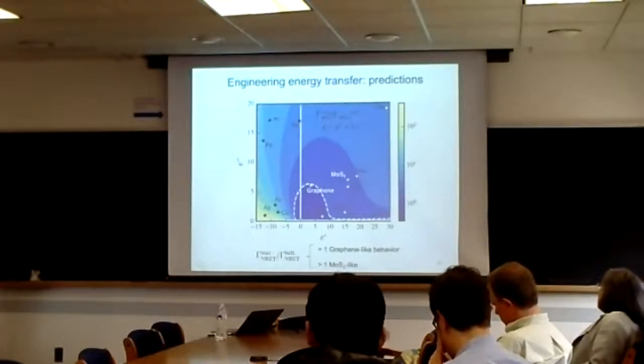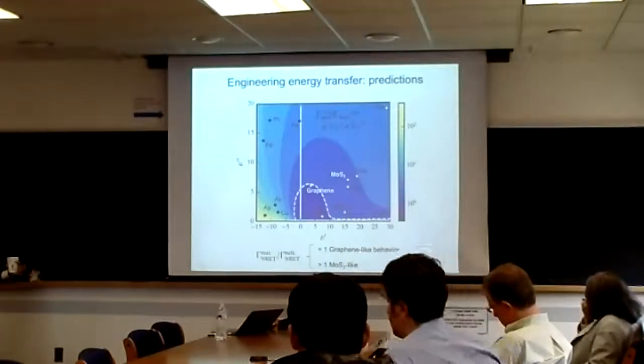Most materials are at around 2 eV. Of course these dots will emit at different frequencies, and you have different dielectric functions. Most of the technologically useful materials here are behaving like MoS2. Just as an example, silver metal screens very heavily, it's metallic, it screens a lot. So a monolayer of silver or a nanometer of silver would be 1,000 times more efficient at this non-radiative energy transfer than bulk silver. In the past, people have also measured energy transfer to silver surfaces in the 70s and 80s, and it essentially looks like a 2D sheet because you only see the first monolayer of it.